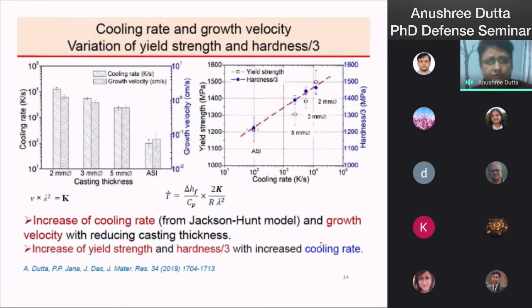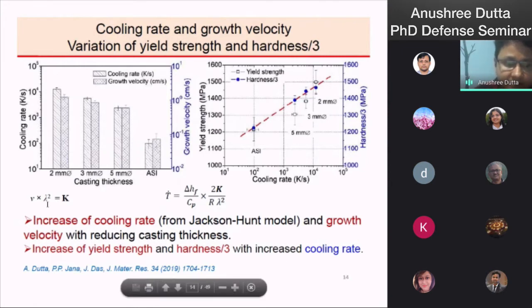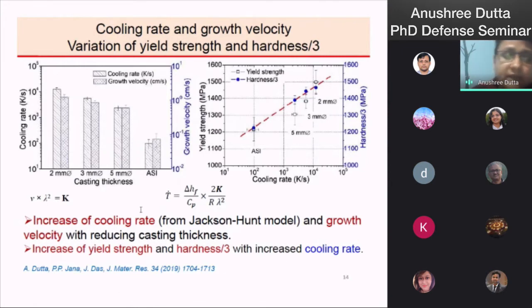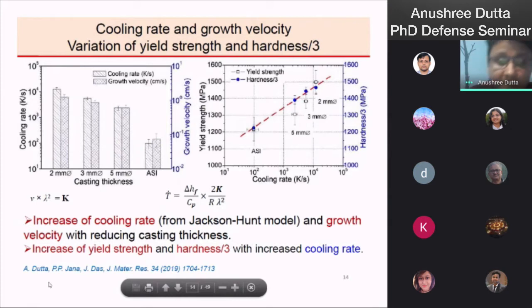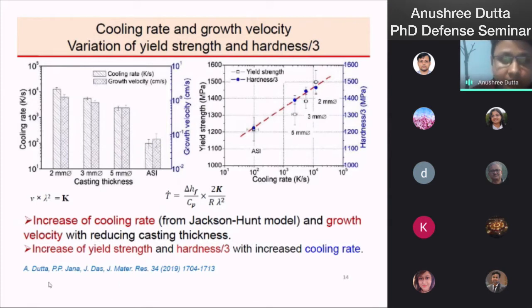The cooling rate and growth velocity. The cooling rate was estimated from the Jackson-Hunt model, using these two equations. The cooling rate for the 2 millimeter diameter rod is estimated to be on the order of 10 to the power 4 Kelvin per second, and the cooling rates for all the diameter rods are given here. The variation of yield strength and hardness with cooling rate is plotted in this diagram. It shows that the yield strength and hardness increase linearly with the cooling rate.